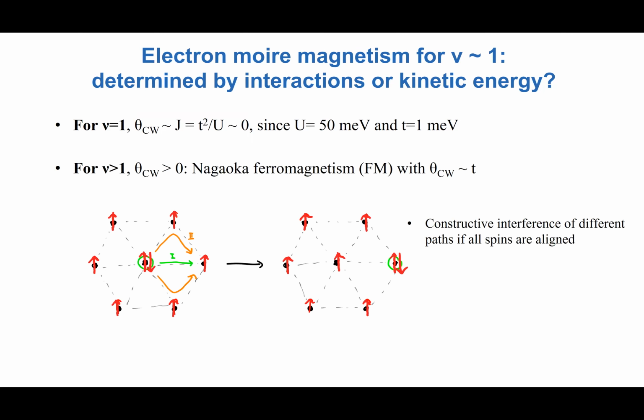Now, if you go to nu larger than one, things can change, because what now determines the low energy physics is that you have these doublons, and the configuration that maximizes the delocalization of the doublons would minimize the kinetic energy associated with them. And Nagaoka about 50 years ago showed that in such a case a ferromagnetic orientation would ensure constructive interference in hopping and would lead to a minimization of the kinetic energy. In this case, the characteristic energy scale that would determine the magnetic properties is given by t, not by t squared over U. So in systems where on-site repulsion is very strong, you would expect that this could actually be dominant.